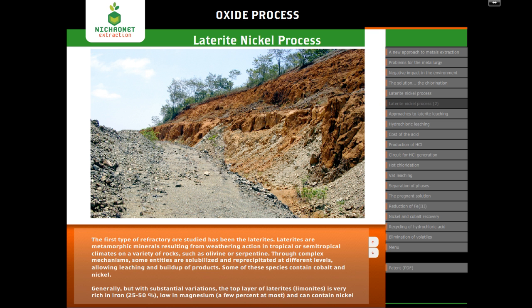At a deeper level, a different composition is found. With this saprolitic level, the iron is much reduced, in the range of 10 to 20%, while the magnesium as MgO reaches values of 15 to 30%. The nickel is also noted to have a concentration above 1%, while cobalt values are somewhat lower than those found in limonite. The refractoriness of such ore results from the presence of relatively large amounts of magnesium and aluminum not compatible with existing technologies.